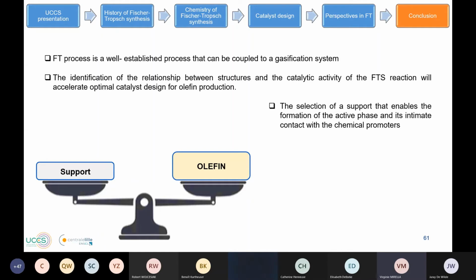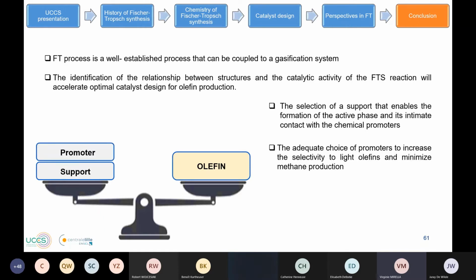What we have seen is that to have better selectivity to olefin, we have to choose the proper support, because the selection of a support enables the formation of the active phase and intimate contact with the chemical promoters. We also have to choose the right promoters if we want to produce olefin. The adequate choice of promoter increases the selectivity to olefin and minimizes the production of methane and higher hydrocarbons.